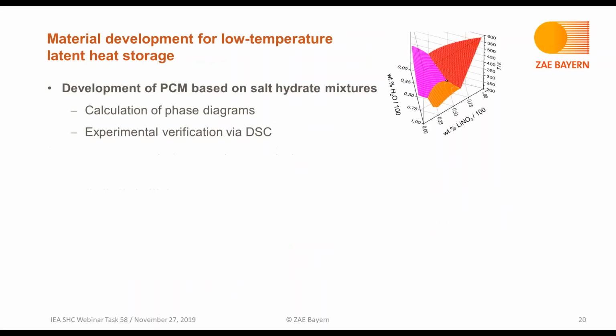So now I'd like to come to the summary of this presentation. Material development of low temperature latent heat storage has been carried out in several steps. The first point is to develop PCM based on salt hydrate mixtures. This is done by calculating solid liquid phase diagrams to identify eutectic mixtures, and then by experimentally verifying the predicted compositions using calorimetry.